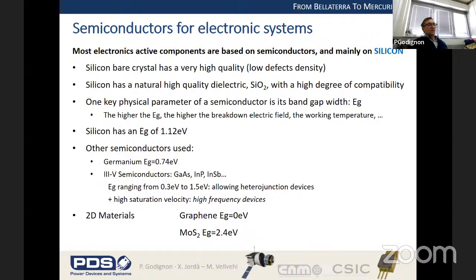And more recently, you have heard about new two-dimensional materials. The most famous is graphene, but graphene has a gap of 0 electron volts. So it's not really a semiconductor. You cannot build a transistor with pure graphene. This is why now there is a lot of research oriented to other 2D materials, like molybdenum disulfide, which have a gap more similar to a standard semiconductor, and then could be used to build some electronic functions.